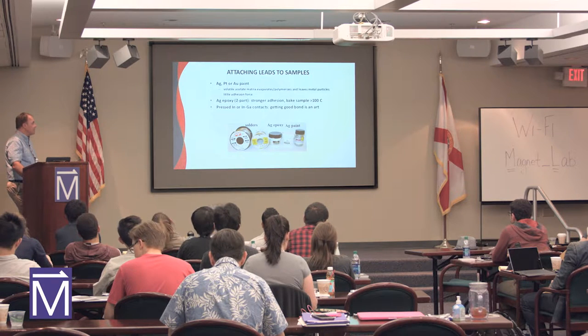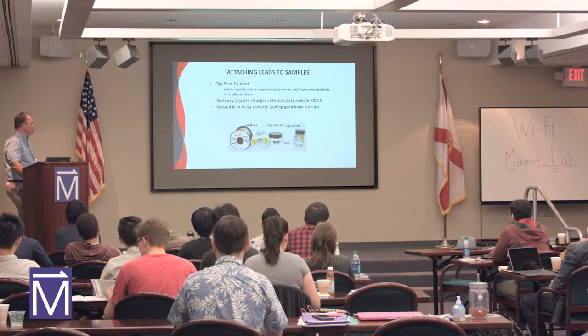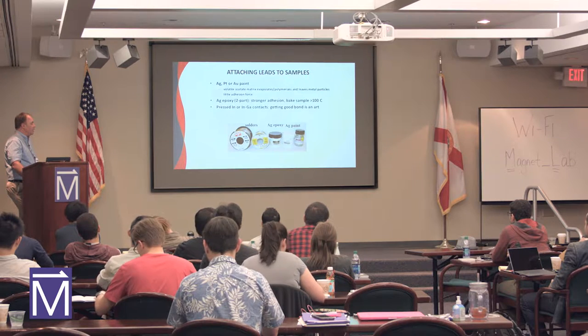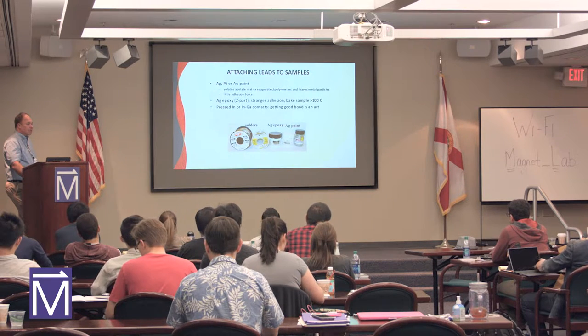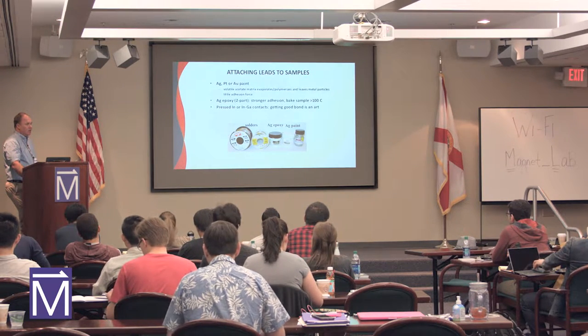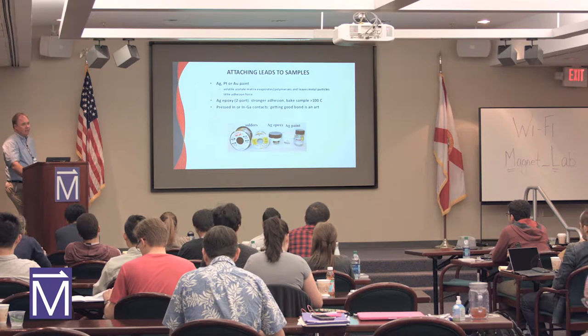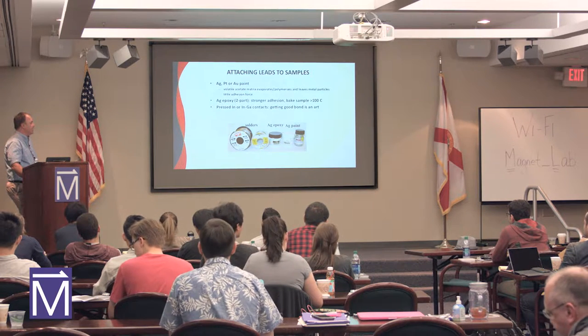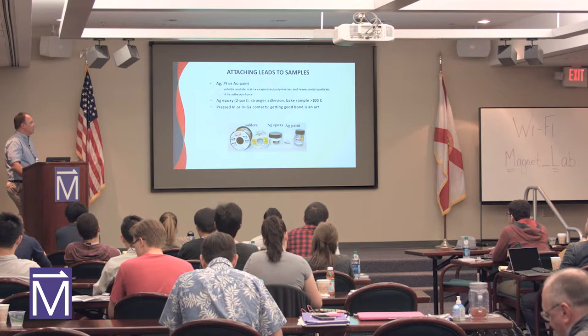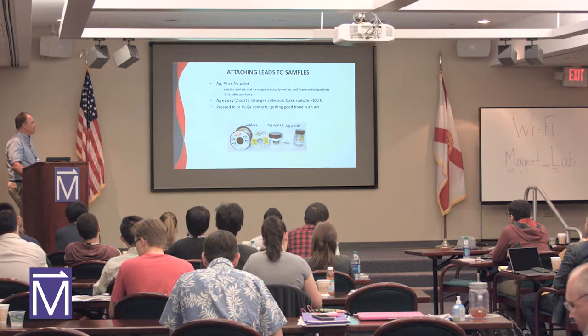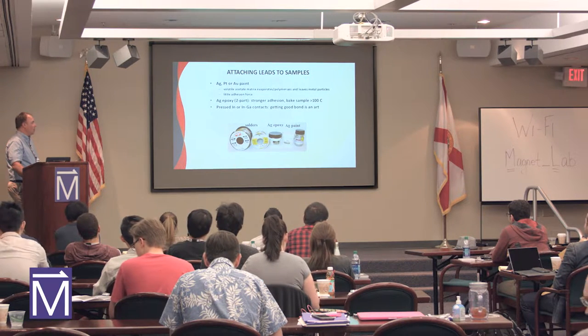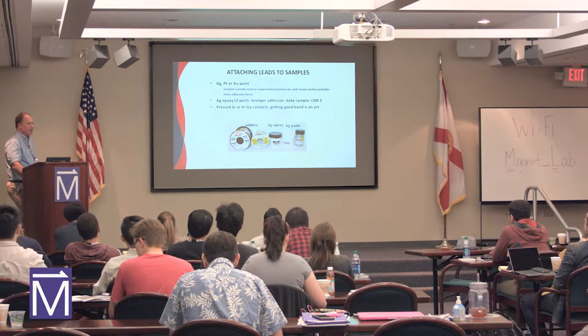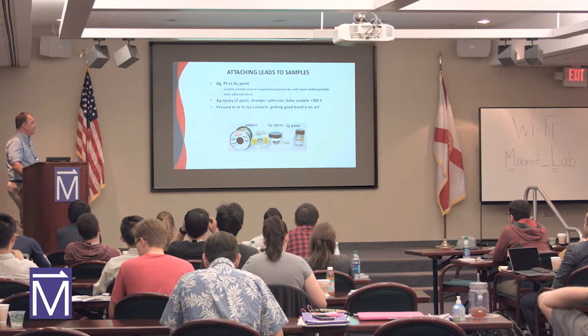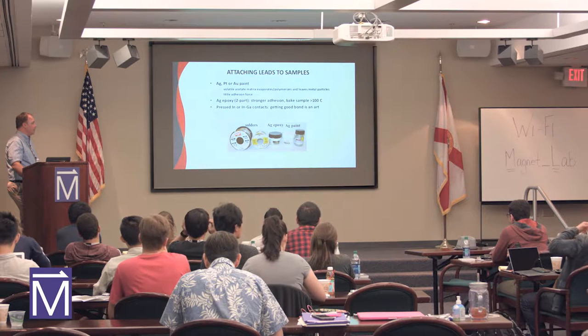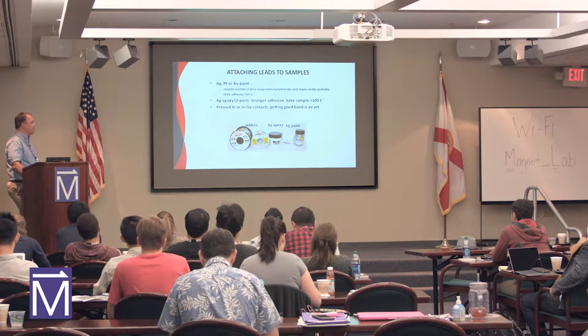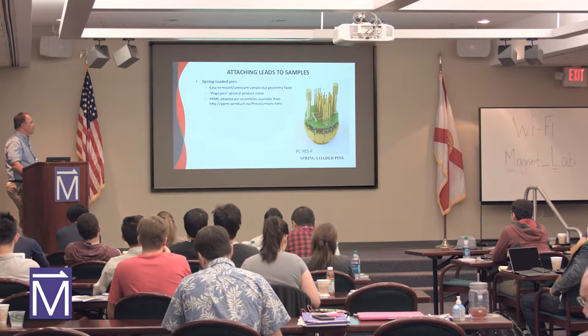Silver paint, easy way to go. You have to worry about the outgassing, so you have to make sure your paint is dry. So you typically bake that to make sure that the solvent's out of the paint. Two-part epoxy, once again, you need to bake these things out. You have better adhesion with the epoxy. They may work better above 100 C, or indium press contacts.